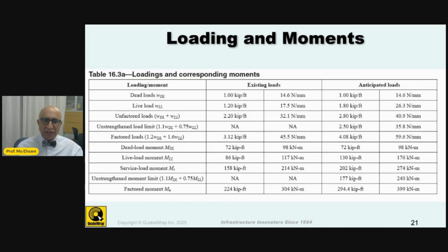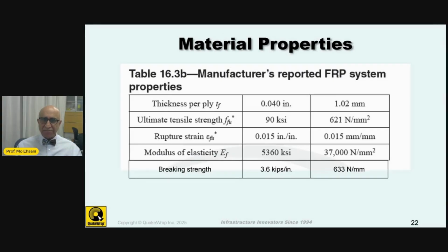So for example, the second one from the bottom, they say that the unstrengthened moment limit should be 1.1 dead load plus 0.75 live load. So you cannot have anything less than that, and so those limits guide you such that you can't say I'm going to increase the capacity of this beam by 3 times. You can only increase it by roughly 35 to 45, maybe in some cases 50%, based on these factors or checks that you have to do.